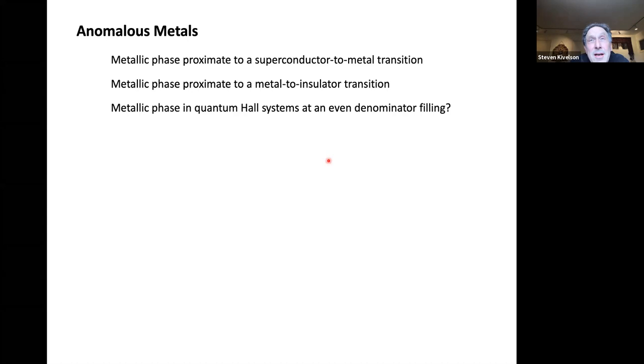Bad metals manage to get their resistivity to be much higher than that. On the one hand, there's something, I don't know if it's coherent, that's strongly temperature dependent, because their resistivity continues to be very strongly temperature dependent. On the other hand, their resistivity is much bigger than the quantum of resistance. So there can't possibly be coherent quasi-particles. Where there are coherent quasi-particles, they would carry the current and the resistance would be much less. So I agree with you that they're a type of incoherent metal, but they have something else that makes them even worse than an incoherent metal.